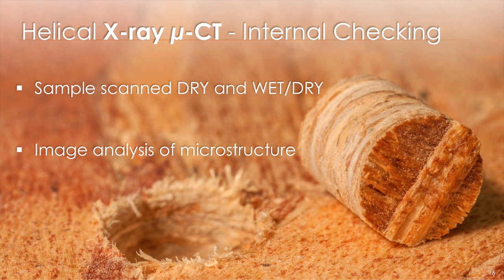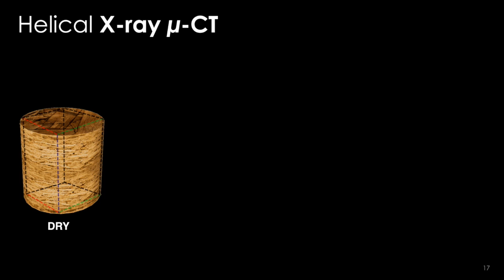So with the Helical X-ray CT device, we used the same sample before and after swelling, a cylindrical sample this time, measuring 10.5 millimeters by 10, as you see in the photo. The swelling was promoted by soaking the cylindrical sample for 48 hours under the water. And then we studied the microstructure of OSB using image analysis.